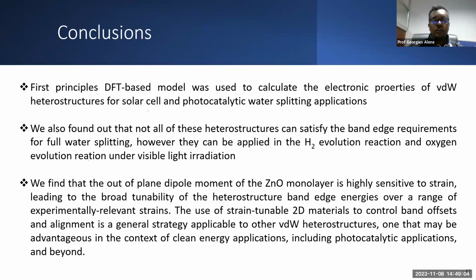The other thing we found out is the dipole moment of the zinc oxide monolayer is highly sensitive to strain. As I showed, when we apply compressive strain, it is significantly affected. And this leads to broad tunability of the heterostructure. So we can tune the properties of heterostructures using strain over a range of experimentally relevant strain values. So the use of strain-tunable 2D materials to control band offset and alignment is a general strategy, which can be applied to other van der Waals heterostructures.